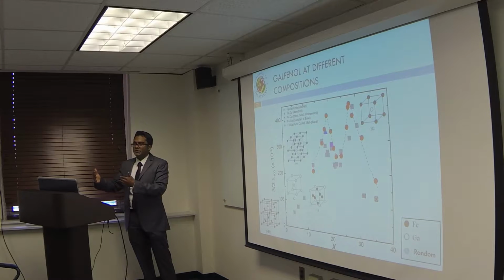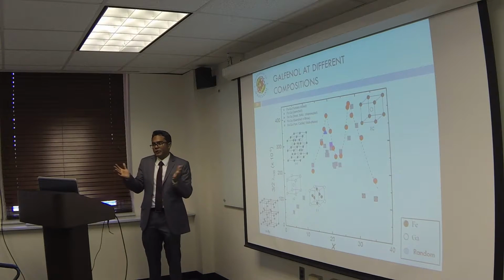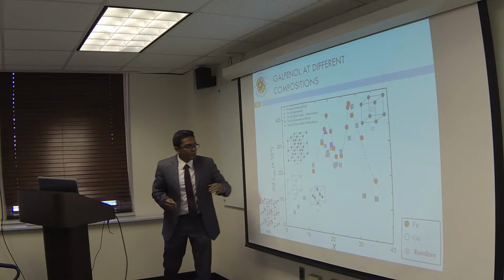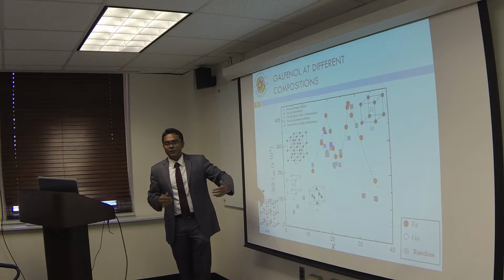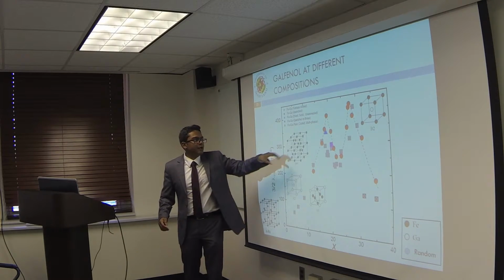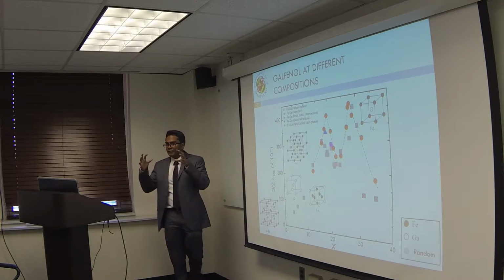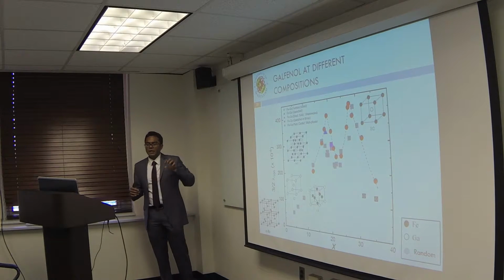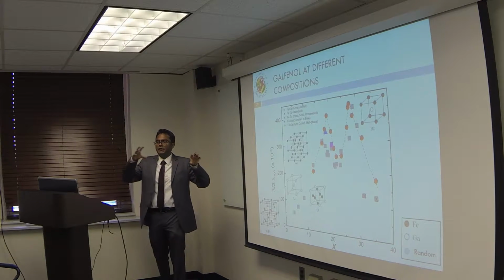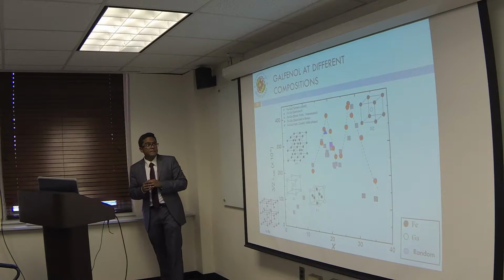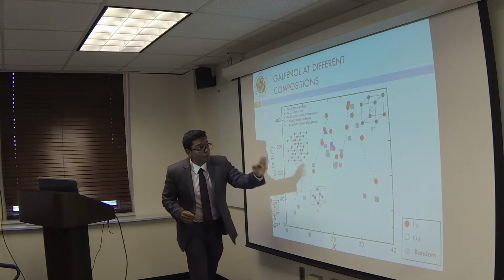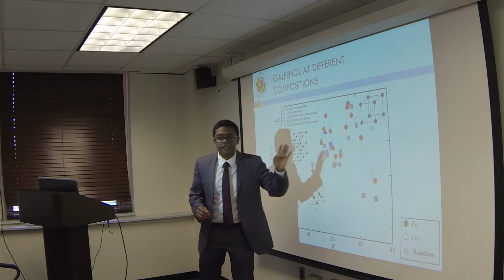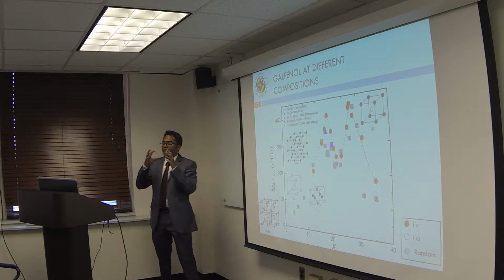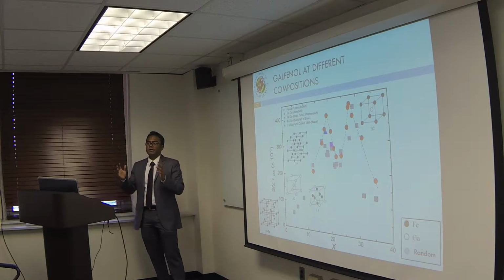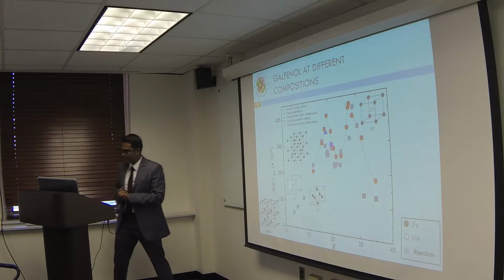And these are more interesting to study because when it's very random, you get very random results. So past 12% or around 15%, you would get into the DO3 phase where you have iron atoms at all the corners, and you start having gallium atoms at alternating centers of the unit cells. And as I keep adding more and more gallium, you get into the B2 phase past 20%, where you have a gallium atom at the center of every unit cell in the crystal lattice.